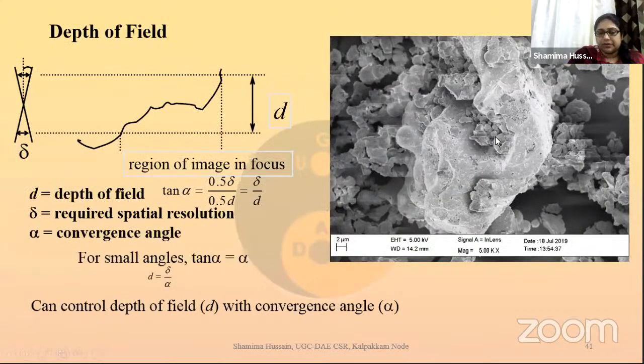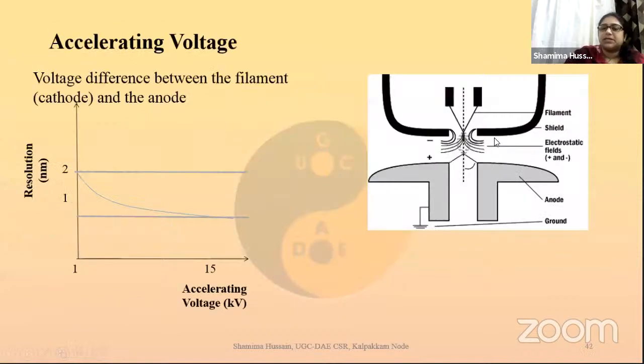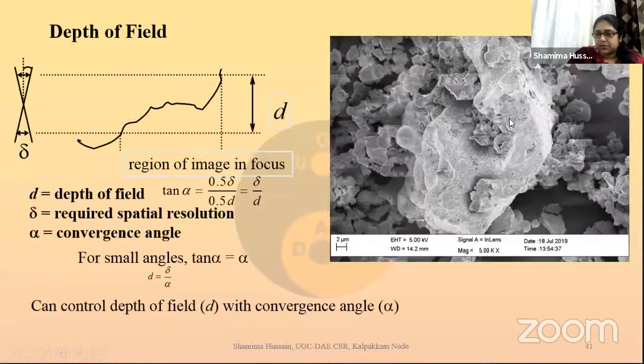Depth of field, yes, this is very important. This comes with the focusing that we discussed. If I were to focus on this sample, which has a rough surface, the sample height is different. So if I focus on the surface, definitely this area doesn't fall under my focus, so it becomes under focused. However, if I try to focus on features which are much lower in the depth, then these become over focused.